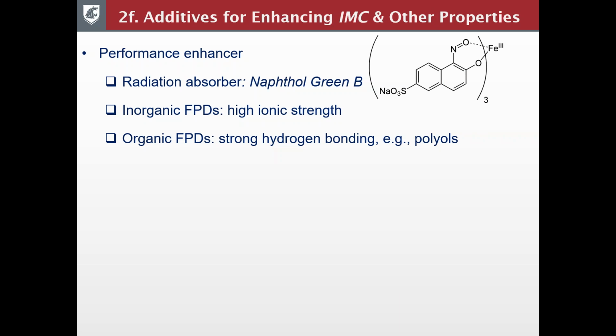And beyond corrosion inhibitors, there are other additives for enhancing the performance, such as melting capacity and other properties. So in the book chapter, we look at the patents or publications of the last decade or so. We found a few very interesting ones, like the use of radiation absorber, which tends to be at a lower concentration, of course, no more than 1,000 ppm. But in these cases, it tends to absorb UV light and thermal energy from the environment, and therefore enhance the deicer performance. And also, oftentimes, there's a mixing of inorganic freezing point depressants and organic ones, because the inorganic freezing point depressants tend to have higher ionic strength due to their lower molecular weight. So given the same concentration, they have higher ionic strength.